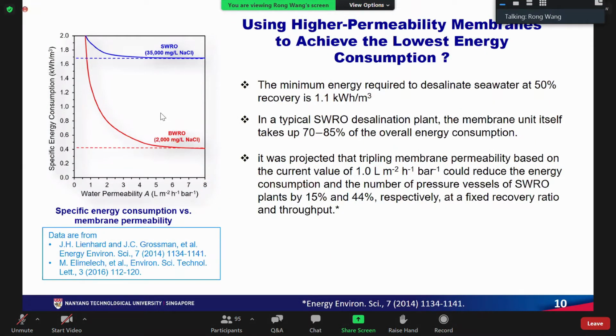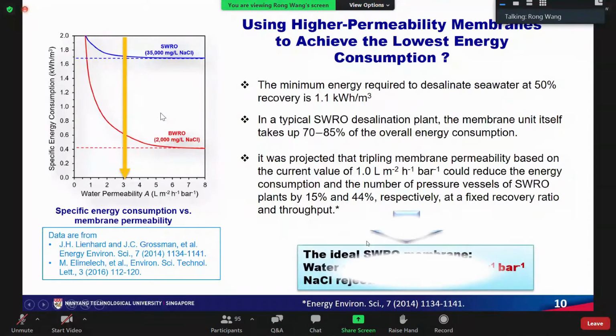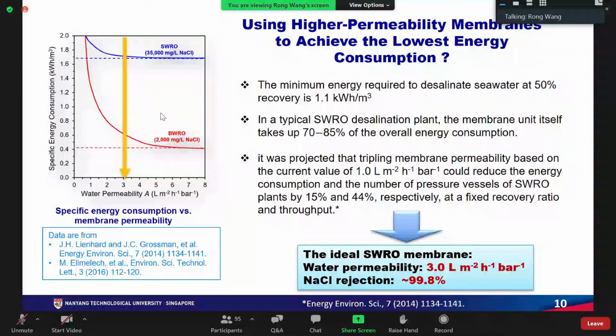You may ask, how high is the upper limit of SWRO membrane's permeability that can help to achieve the lowest energy consumption? Well, a lot of researchers have worked out the relationship for the specific energy consumption versus membrane permeability, as shown in this figure. For SWRO, it was projected that if water permeability increased from 1 to 3 LMH per bar, the energy consumption and the number of pressure vessels of the SWRO plant can be reduced by 15% and 44% respectively. In other words, the ideal SWRO membrane should have water permeability around 3 LMH per bar with sodium chloride rejection around 99.8%. This refers to seawater.